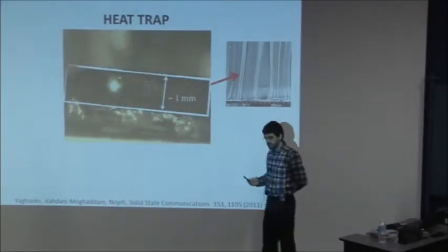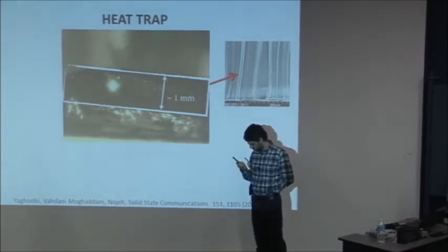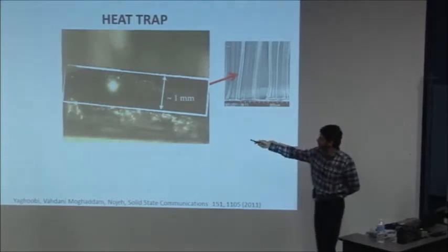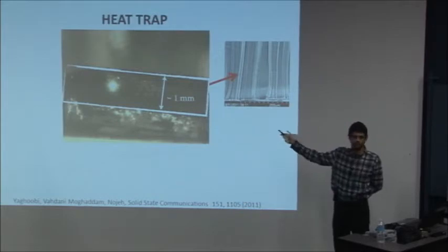And the reason is because the heat is not spreading to a wide area, it remains localized. You don't need to put in too much power to heat it up. So the lowest we've ever gone, I don't know how much the power of this laser is. Okay, maximum output power, it says 5 milliwatts. The lowest power we've ever tried and gotten this kind of thing is 4 milliwatts.